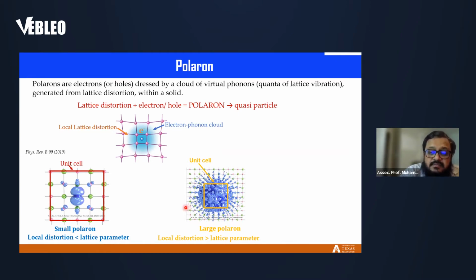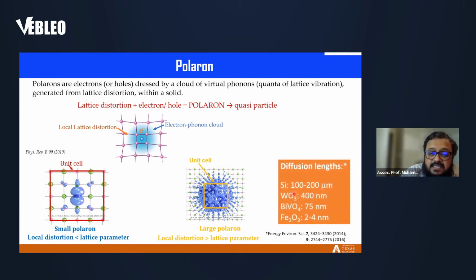Now, the polaron, as the previous speaker mentioned, does impact the photoconduction or conduction in materials. A quick view of that. If we consider silicon, the diffusion length is a bit higher than micro, 100 to 200, sometimes even more than 200 micrometer level. Once we come to bismuth vanadate or iron oxide, these both have 3d electrons. Bismuth vanadate has vanadium 3d, iron oxide has iron 3d. Then as you can see, the diffusion length drops significantly, more than 4 orders of magnitude. So this is what happens when polarons form in materials.